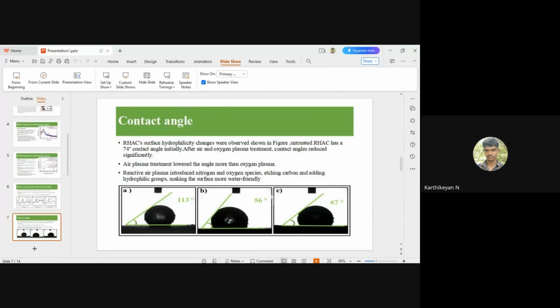In the contact angle analysis, the RHAC surface's hydrophilic nature changes were observed, as shown in the figure. The untreated RHAC has a 74-degree contact angle initially. After oxygen and air plasma treatment, the contact angle reduced significantly. The air plasma treatment lowered it more compared to oxygen and untreated RHAC. The reactive air plasma introduced nitrogen and oxygen species, etching carbon and adding hydrophilic groups,